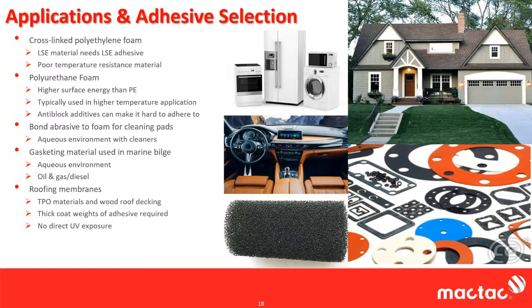The reason why is that if you're talking solvent acrylic, you've got to dry the adhesive. And if you're talking UV acrylic, although we can get much thicker in our UV acrylic coat weights, you still have to be able to cure through them. With rubber and hot melt processing, really all they do is cool. So as much as you can pump and lay down is as much as you can coat. So really the sky's the limit. For some of our GS products, we coat up to 50 mils thick.